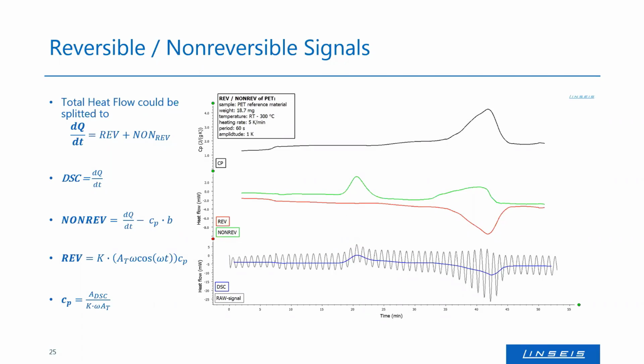So again, some theory. The total heat flow is the reversing heat flow plus the non-reversing heat flow. So the non-reversing heat flow is the total heat flow minus the CP multiplied with the heating rate, and the reversing heat flow is the calibration factor multiplied with the amplitude multiplied with omega, the cosine of omega and time, and of course the CP. So this is how we get the value of the CP. Basically, the CP is defined as the amplitude of my DSC signal, which you can see here in the gray measurement, divided by the calibration factor multiplied with my period, so omega, multiplied with the amplitude of my temperature. This is how we receive the values for the CP and also for the reversing and non-reversing heat flow.